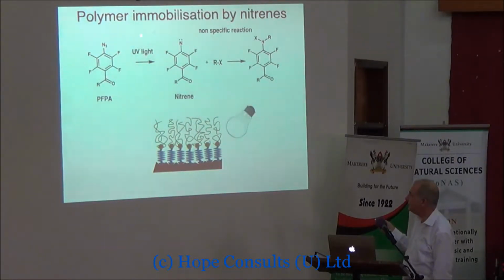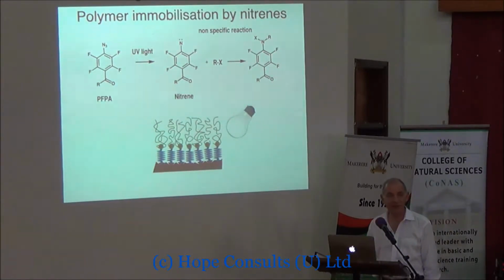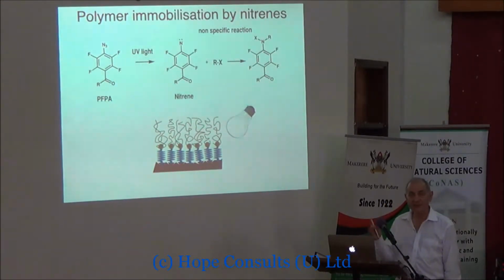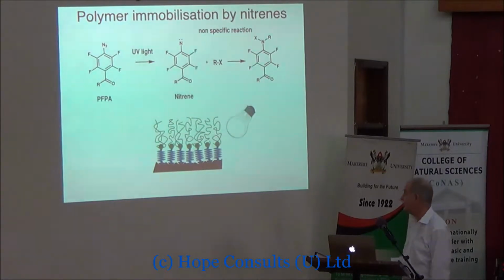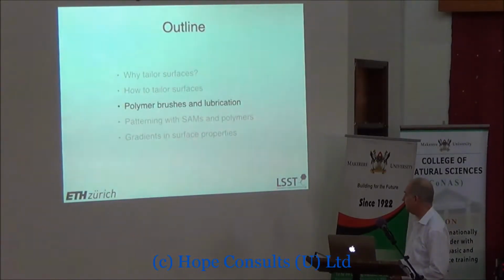N3 gives off N2 under UV light, so it's just nitrogen, leaves this short-lived reactive nitrene species, which then inserts into a chemical bond. Any chemical bond could be one of the bonds in the polymer, and then it fixes it onto the surface. So very unselective chemistry, but very useful for attaching almost any polymer to almost anything, and making almost a polymer brush.